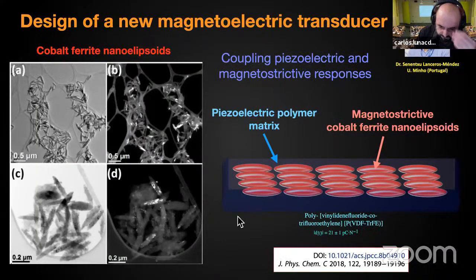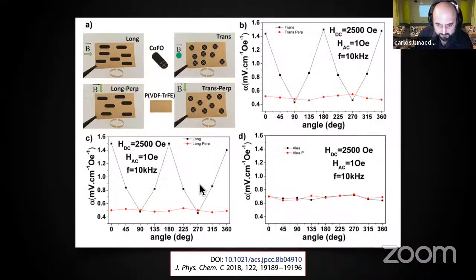In collaboration with the group of Dr. Senentxu Lanceros, we designed a new magnetoelectric transducer based on the coupling between the piezoelectric properties of a polymeric matrix with the magnetostriction properties of cobalt ferrite nanoellipsoids. The nanoellipsoids are aligned, as you can see, and we obtain very nice results.